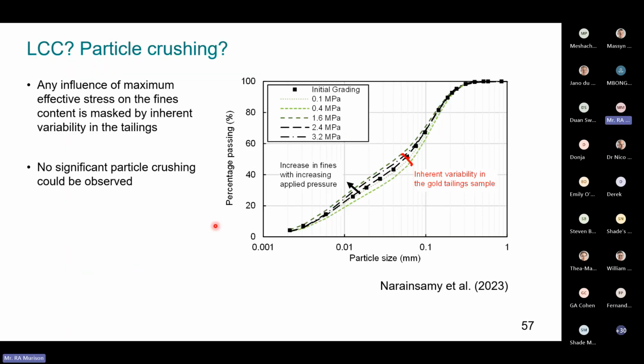What you might say is, how do you know that you've not traversed onto the limiting compression curve, and that's why you're occupying the same space for each of these compression paths? Well, as I said, we did gradings before and after each test. So the markers that we have here are the average initial grading, and then we've plotted the maximum stress which any sample had experienced versus grading curve. And what we see here might be some evidence of a marginal increase in fines content if we look at the 2.4 MPa sample, then the 3.2 and the 1.6. But then we go and look at the 100 and 400 kPa samples, and somehow the fines content has reduced, and that's certainly not possible if you have a unique initial grading.